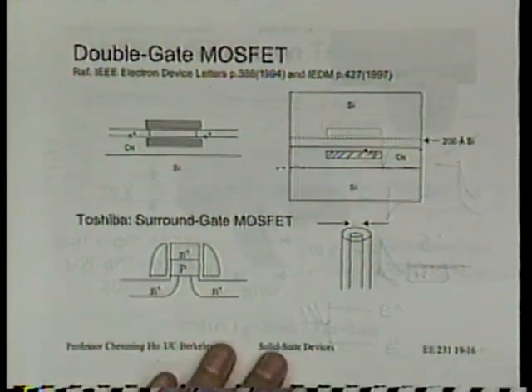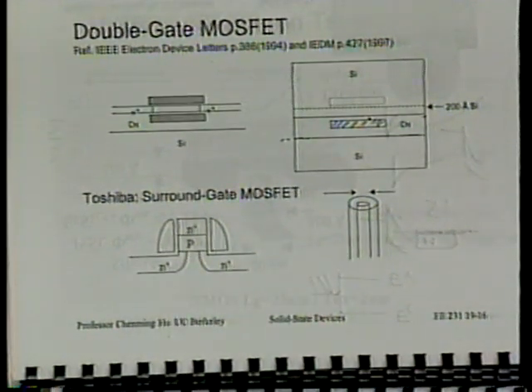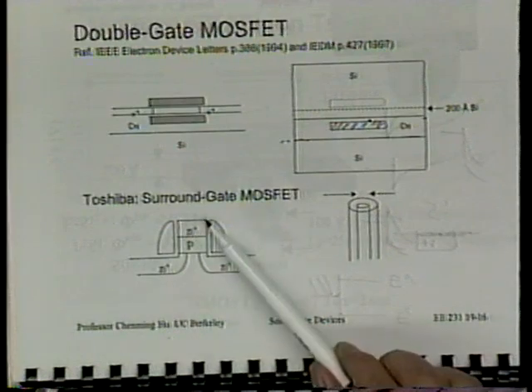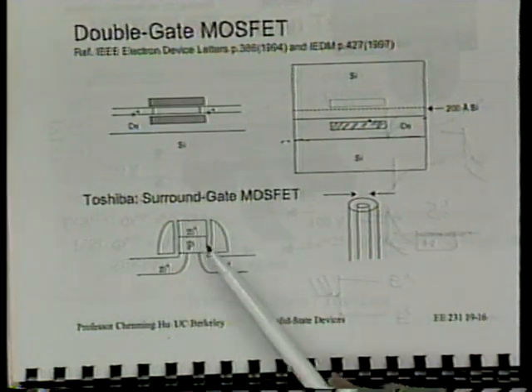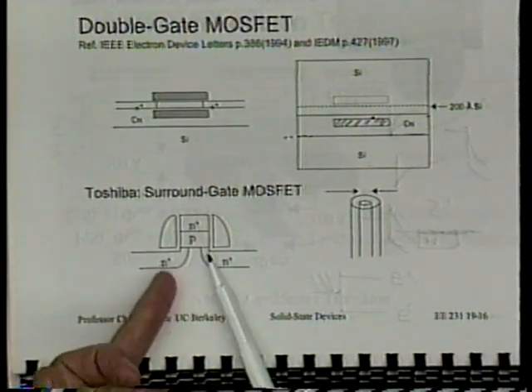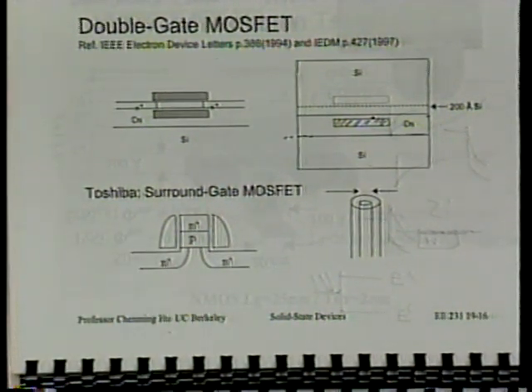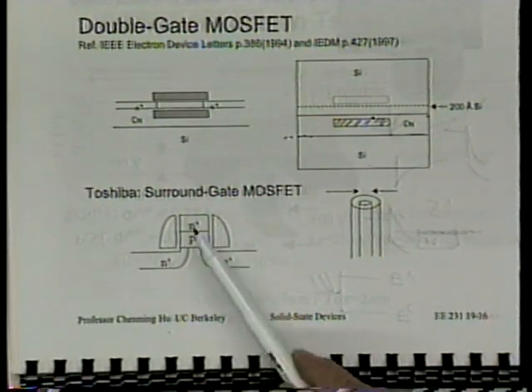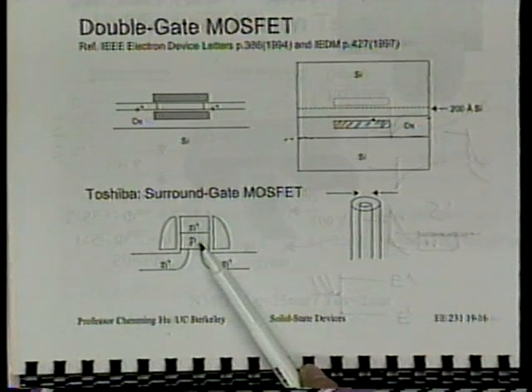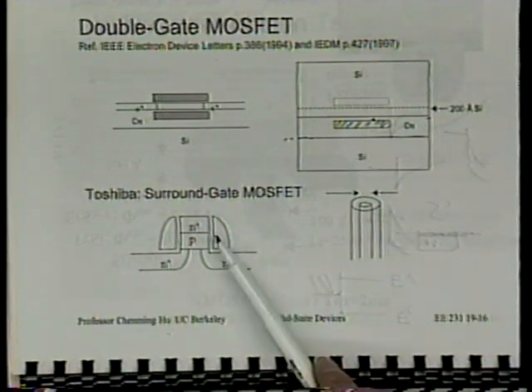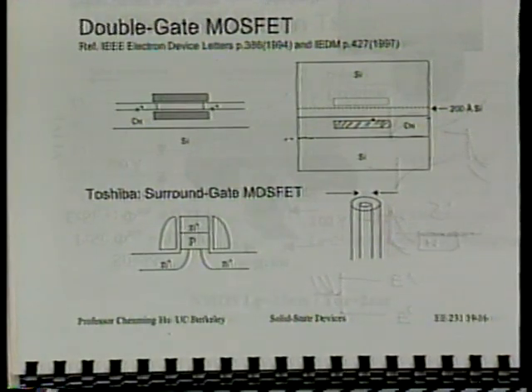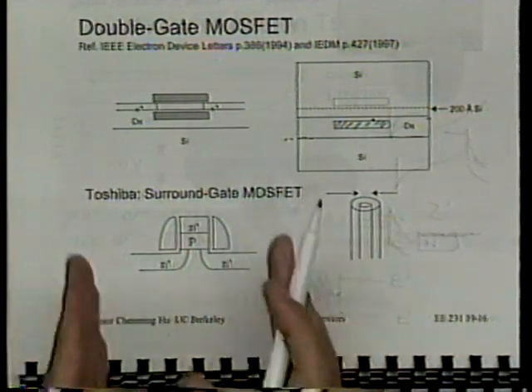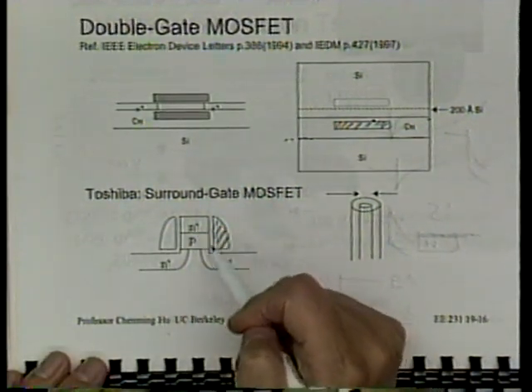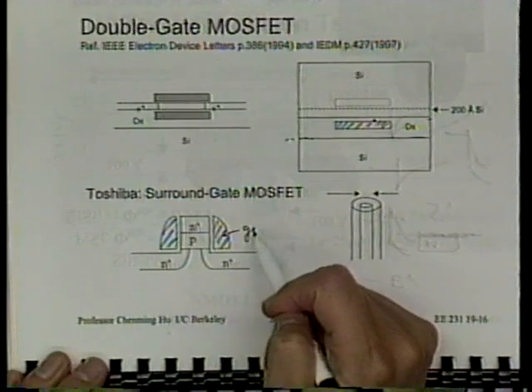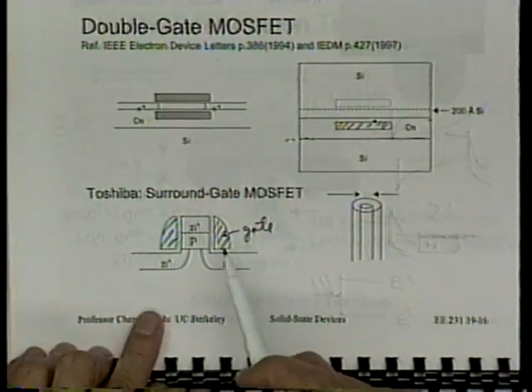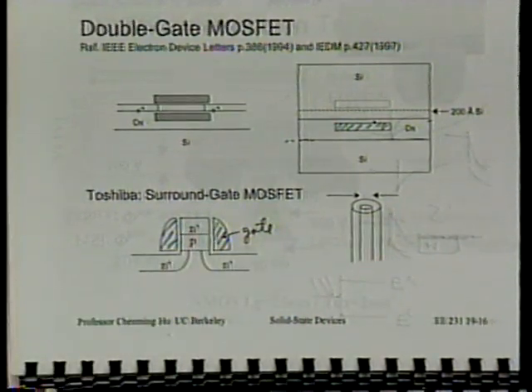So other ideas people have done is Toshiba has something called a surrounded gate MOSFET. You will etch a pillar in this or a short wall of silicon in the silicon substrate. All right? And then either due to epitaxy or just implantation, you create this situation, N plus on top and here. You grow the gate oxide and you put down polysilicon spacer. Remember spacer idea? You can put down a material that only surrounds the side wall, right? So you make this polycrystalline silicon spacer. They are the gates. Now do you see what happens? You have a gate on one side, gate on the other side. So this is double gate, is that right?